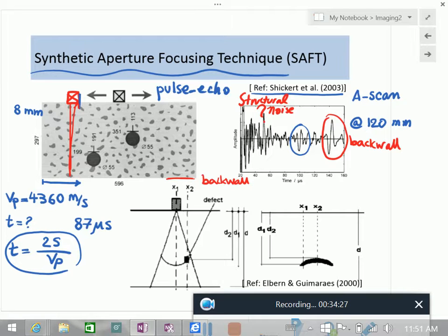And if you compare this, you know how to calculate signal-to-noise ratio. If you compare this, you see that the signal-to-noise ratio is not very great. And remember, this concrete has a very small aggregate. If you are the civil engineers in the room, you know that 8 millimeter aggregate is very small, right? You agree with me? So even with that, you have this kind of noise.